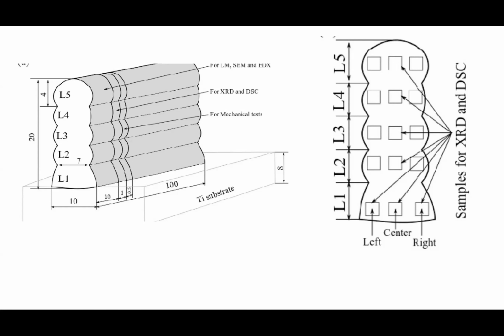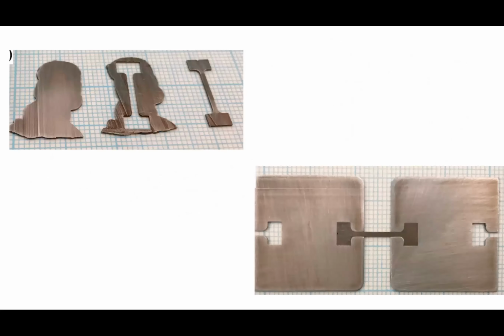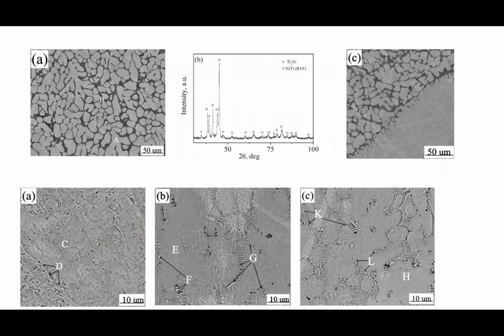We could easily fabricate the structures, and when we analyzed them, no cracks were observed, because in most of these cases we used a substrate heating of around 250 degrees Celsius in order to maintain homogeneity. To understand the behavior, for the first layer we took samples at different points: at the left, at the center, and at the right, and we analyzed the microstructure. This is a closer view of the microstructure. In the first layer, there was a mixture of two phases, a dendrite matrix and an interdendrite space.